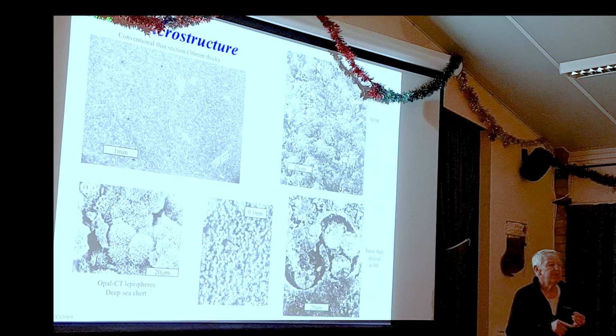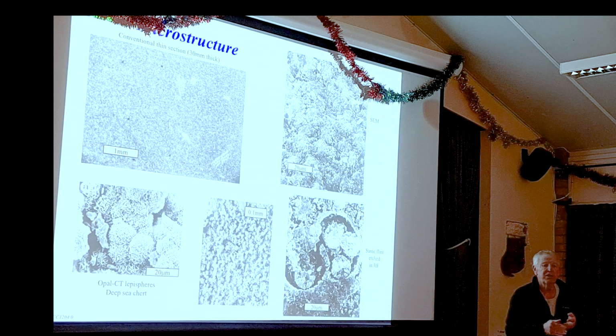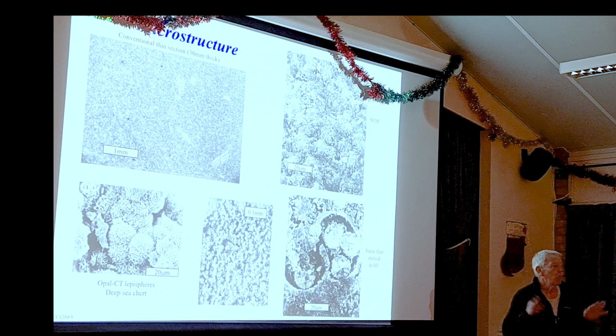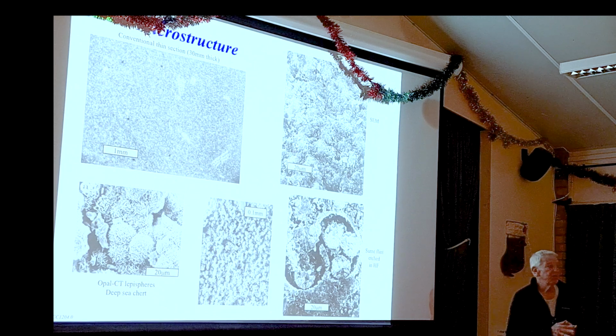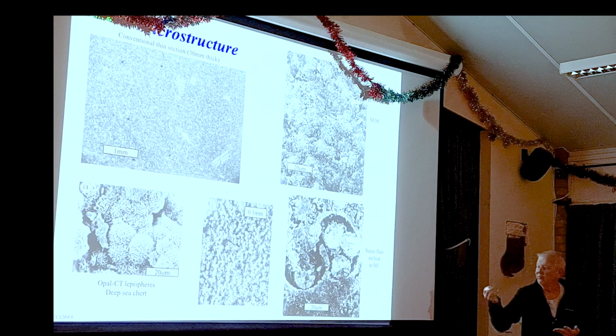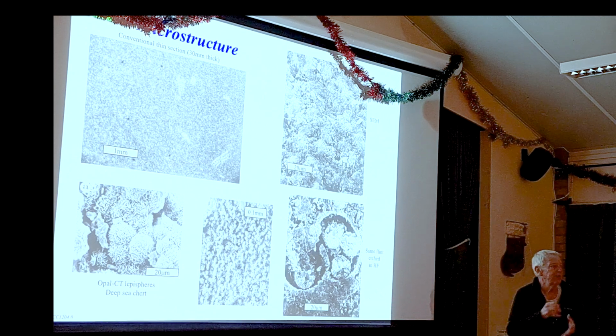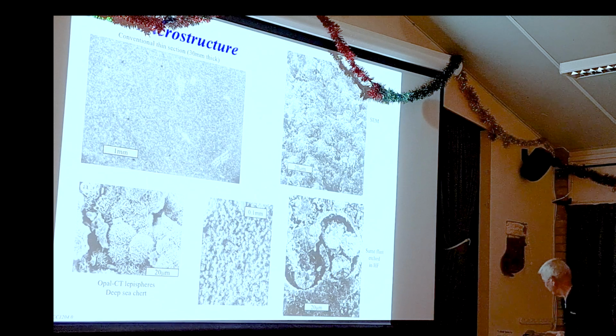And they're composed of a mineral which we call opal CT. It's a bit of a cheat, really. It corresponds to the mineral cristobalite if it's got a lattice defect in one direction, or the mineral tridymite if it's got a lattice defect in another direction. We don't bother arguing about that, we just call it opal CT. And these are essentially how we go from a normal siliceous organism through to a solid silica rock by dissolving the silica and precipitating these lepispheres. They're quite important to our story, as we'll see as I carry on.